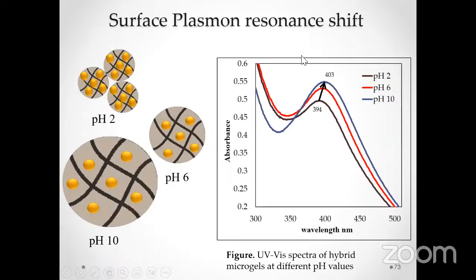Here is again the optical response, showing how we can control it when we change the pH from 2 to 10. Then lambda max has been shifted from 394 to 403. This change in lambda max can be used as a tool for a pH sensor of this system based upon optical response.